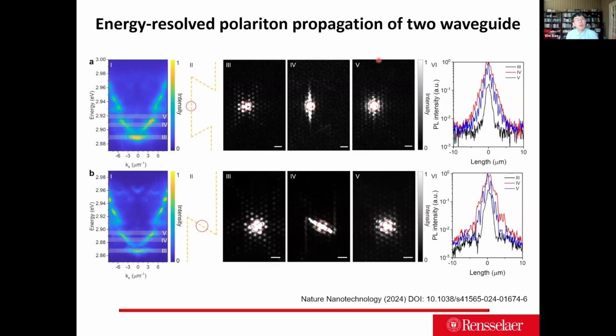So the experimental phenomenon is once you go to 5 times the threshold, you start to see a dark spot, because the PMMA, which is a polymer, starts to be burned out by the UV laser. But the perovskite, you can transfer them and then wash away, they still work. So recently we have a method to get rid of PMMA, so I think the case becomes much better.